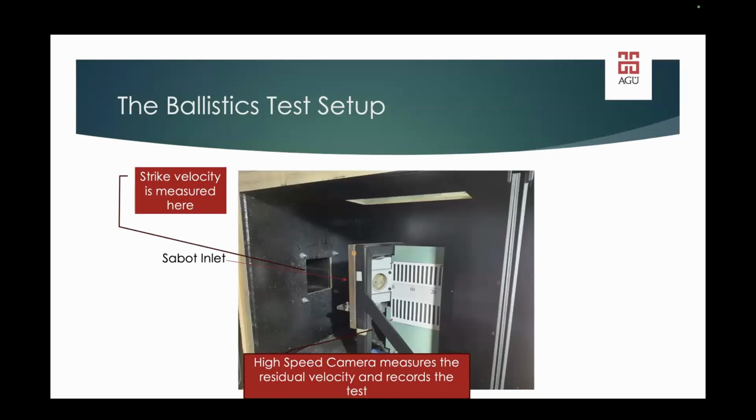Normally, we think that hydrogen embrittlement is much more pronounced at slower strain rate because we give much more time for hydrogen dislocation interactions. Generally speaking, this is correct, and we try to identify the effect of hydrogen at high strain rates. That is why we did ballistic tests. So that is our setup.